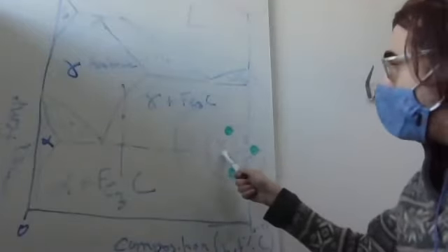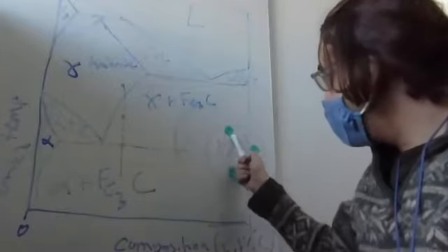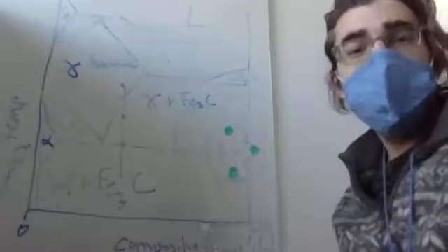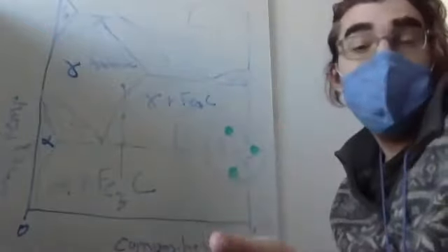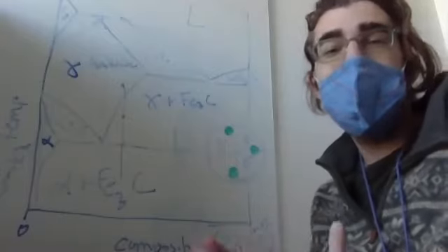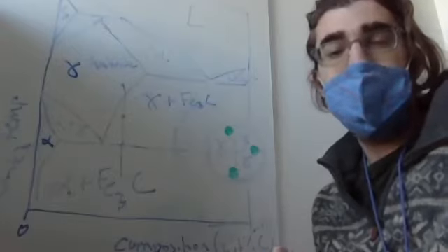So the austenite is going to decompose or undergo a phase transformation, but these cementite crystals won't be affected because they are still thermodynamically stable, right? They're still allowed to exist. I mean, the atoms in there are pretty much happy. So what will happen is the same type of phase transformation will occur as for the eutectoid point, but these cementite crystals will remain unchanged.